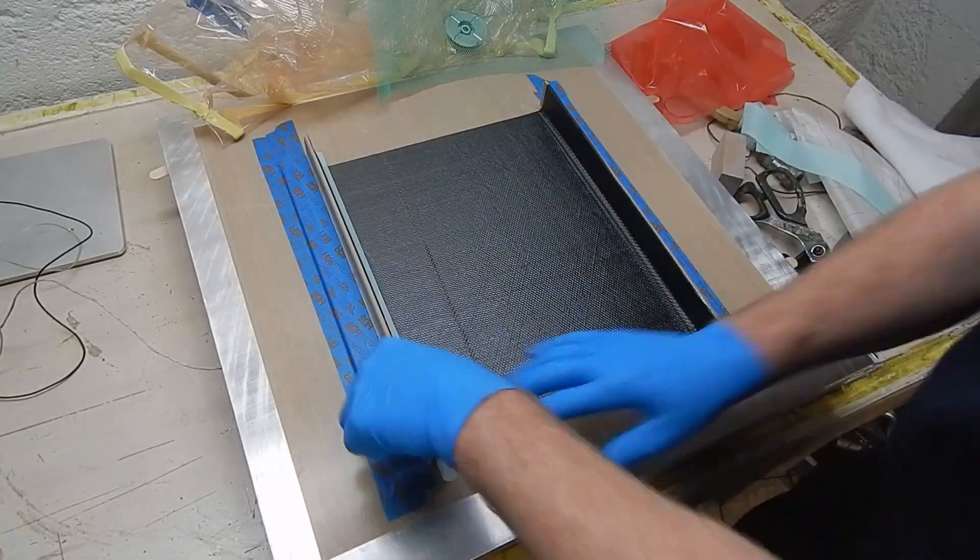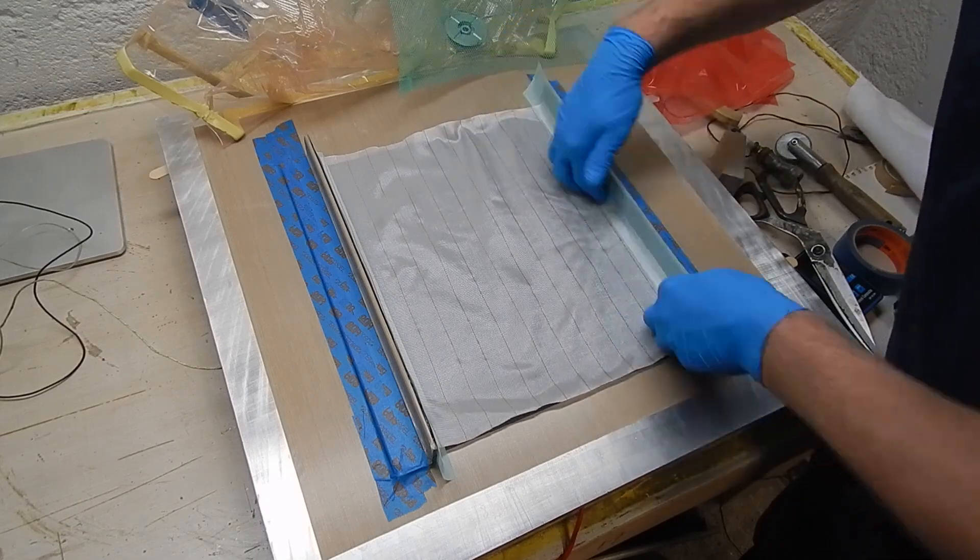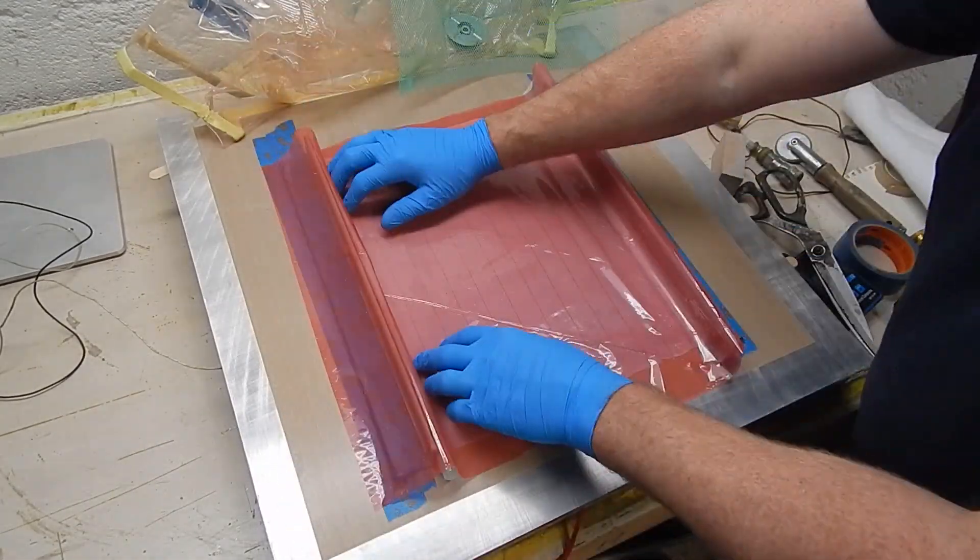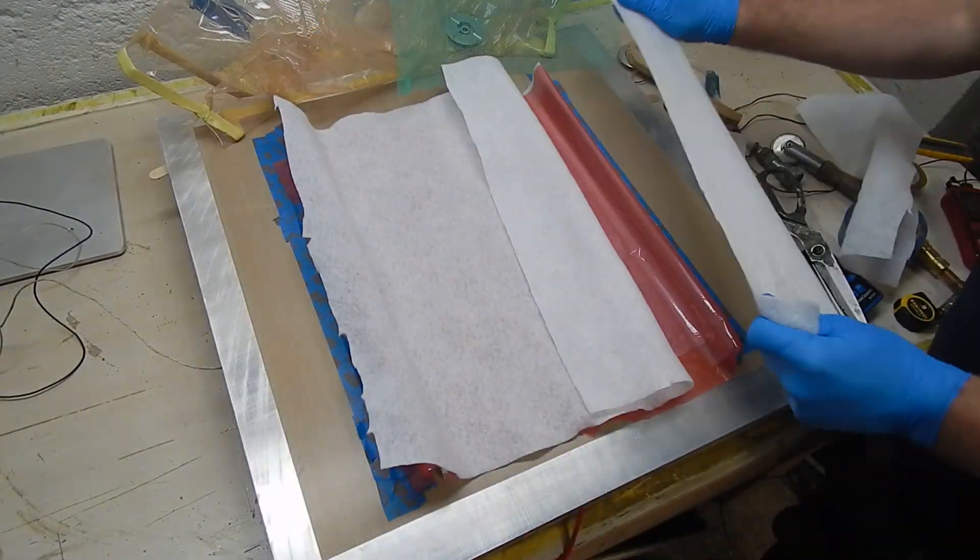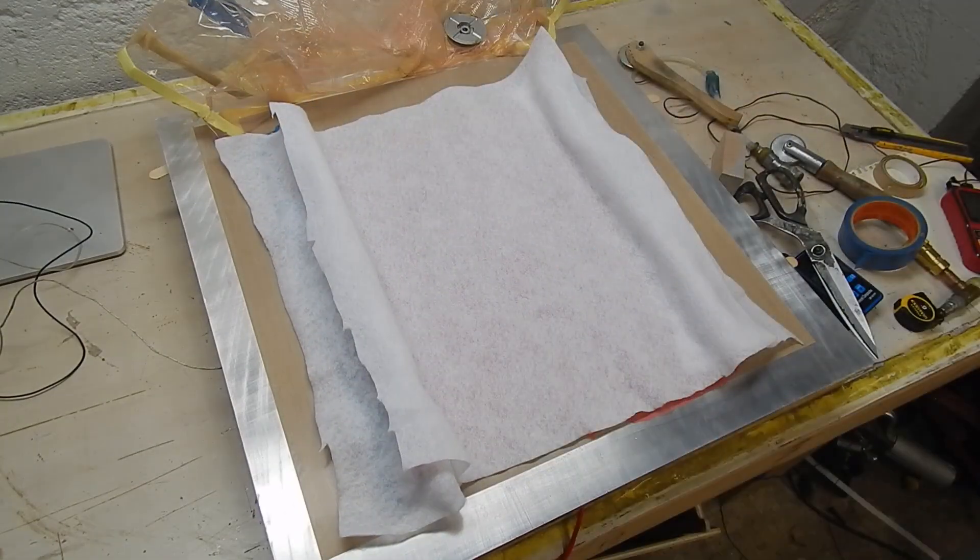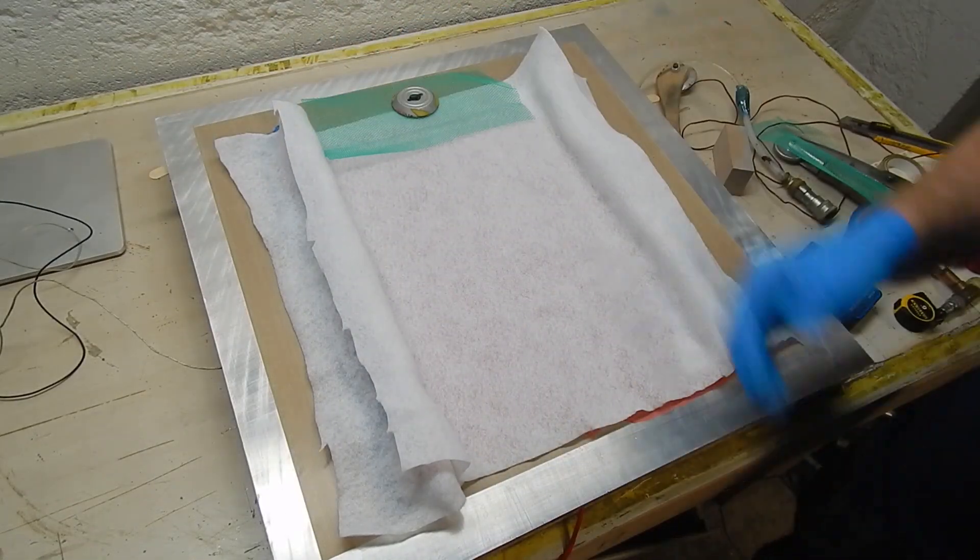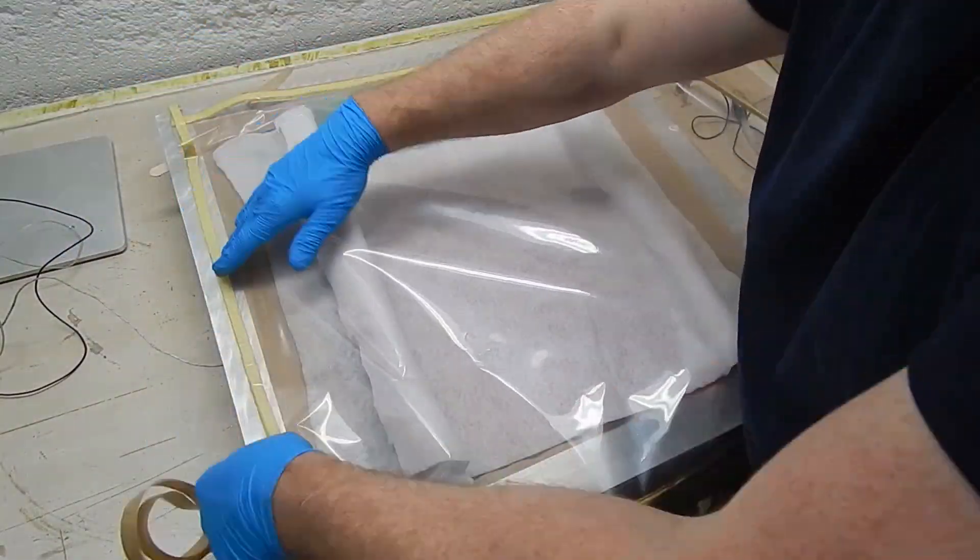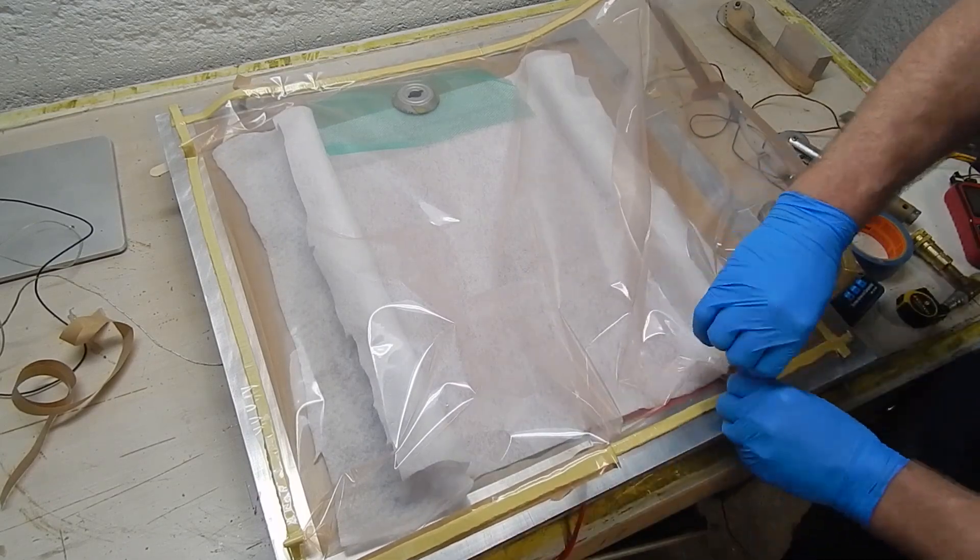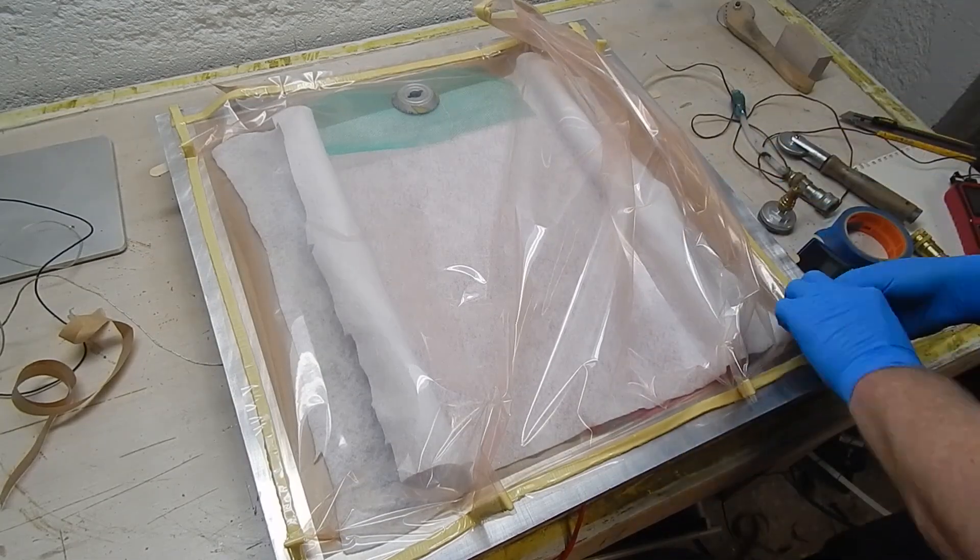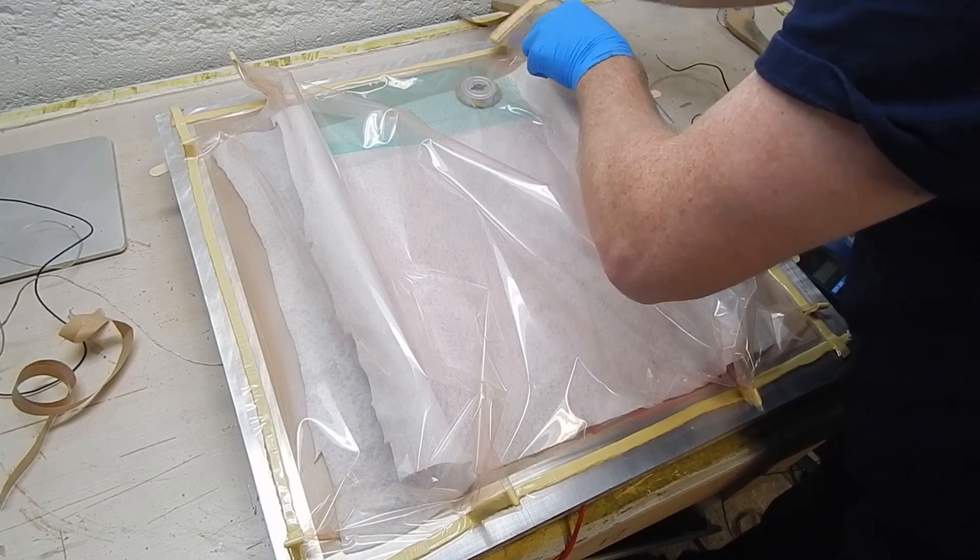And for the process material here, this peel ply is a strip. Comes off a roll. I just used it because it had nice edges. And I made sure not to end the peel ply right in the corner, because sometimes peel ply can get sucked into corners and ends up with a nasty wrinkle. So it's got a ply of that fluoropolymer release film, which I made sure to have enough slack that it won't bridge in the corners. And then did the breather in three separate pieces to cover everything including the perimeter of the flanges where there might be some gaps and things the bag could get sucked into. It's just a good idea to cover anything that might be sharp with breather because even little leaks are bad.